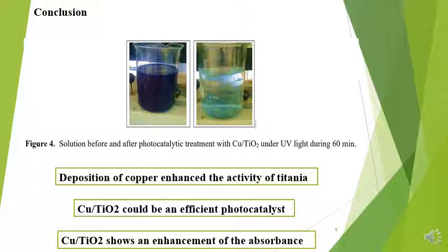As a conclusion, from the results of our work, we can say that deposition of copper enhanced the activity of titania. This significant increase is due to the tendency of the metal to trap electrons from the conduction band of titanium under irradiation, which suppresses the recombination of electron-hole pairs and causes better charge separation. Copper titanium dioxide could be an efficient photocatalyst for industrial textile dye effluent treatment, and it shows an enhancement of the absorbance in the visible region, so this material is capable of working effectively with solar radiation for photocatalytic applications.